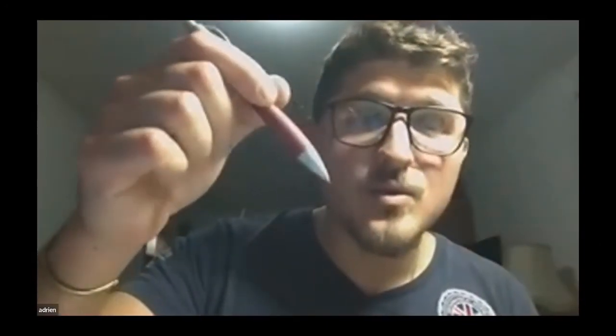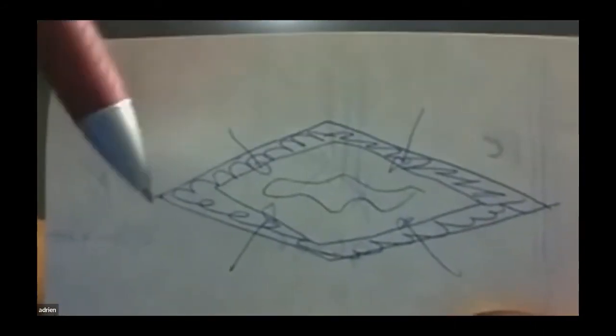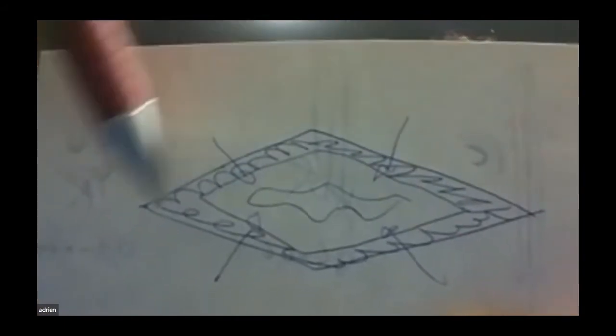The middle of the ingot, in archaeology, when we found them, is often empty. You are not welding the inside. You don't have a press of 20 tons to crunch it. You just have a hammer. So you are going to do the first layer of the ingot, and it's going to solidify. So at the end of the 5 or 6 first weldings, this is what you're going to have: an organized ingot only on the outside.